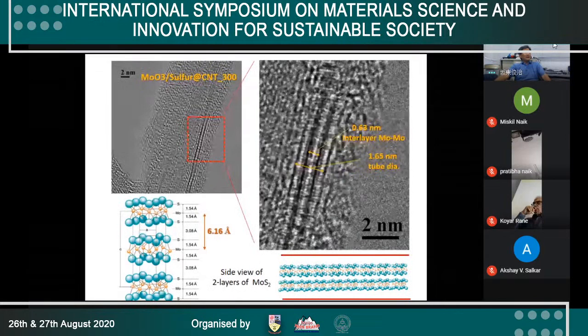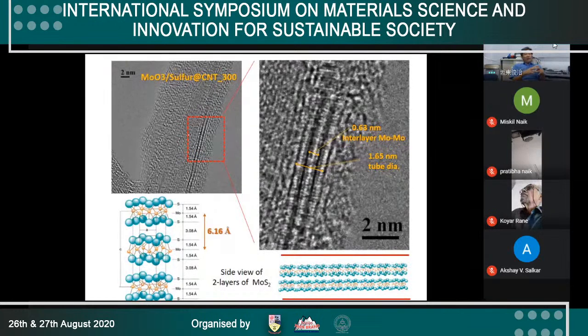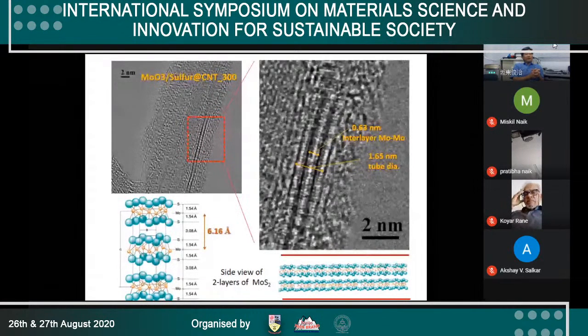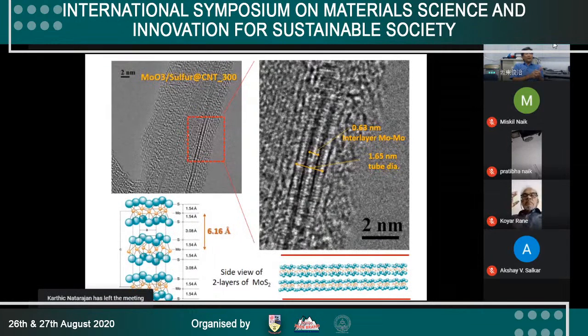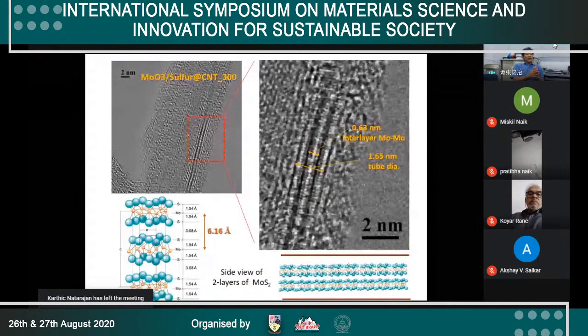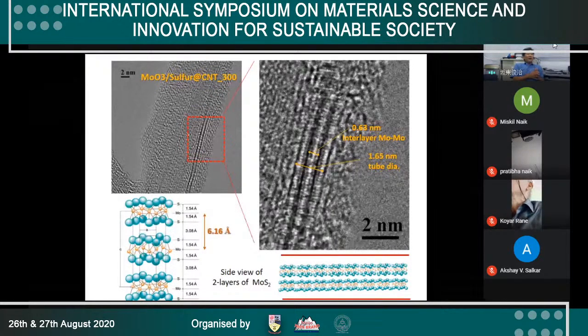Okay, this is a high magnification image of the transmission electron microscope. So that we can see this rectangular circled part. When we magnify this part, you can see the two lines, the black lines inside the nanotube. The nanotube diameter is 1.65 nanometer. This is the tube diameter. This is the two lines. It corresponds to the interlayer molybdenum disulfide distance.